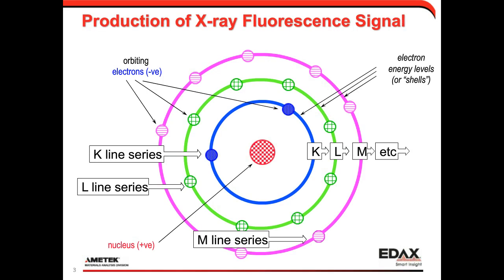Okay, the simplest and shortest way to describe what's going on in X-ray fluorescence: we have a model of an atom here. The X-ray fluorescence technique is measuring the elements themselves. We're not measuring molecules. We're not measuring bonding environments. We measure the element, and when we do thickness measurements, we measure the mass coverage, the amount of element in the material. We get a mass coverage out of that, and then you apply a density number to it to convert that into thickness.